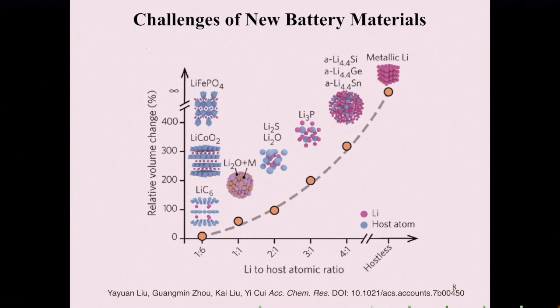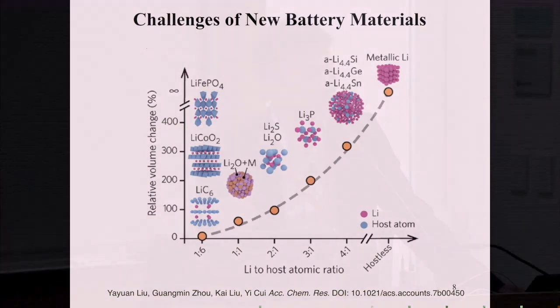But with lithium coming in and out, the relative volume change of this material is very small. You are talking about right here nearly zero, but it's not zero. It's about 10% or less. And your cell phone, your laptop, your electric cars, they are using these materials. To store more energy, you have to increase the ratio of lithium versus the host material until this is virtually infinite, because this is metallic lithium. You don't have any host atoms right there. But the volume change in a relative sense is infinite. So it becomes harder and harder and harder using new materials.